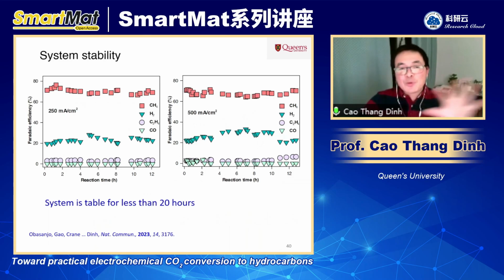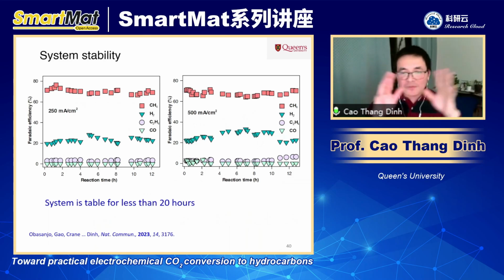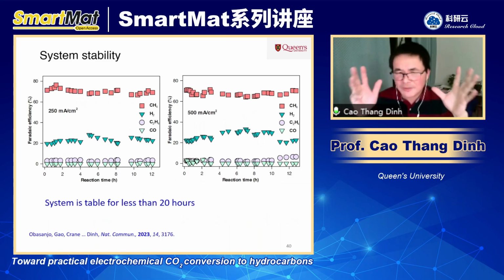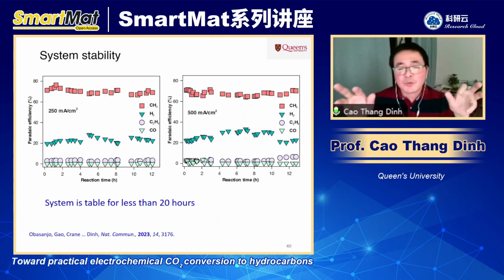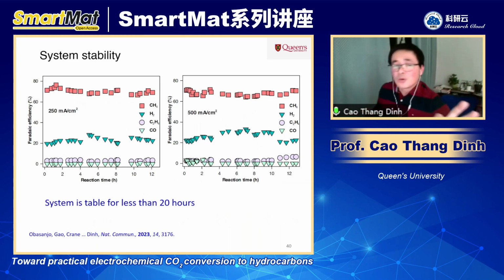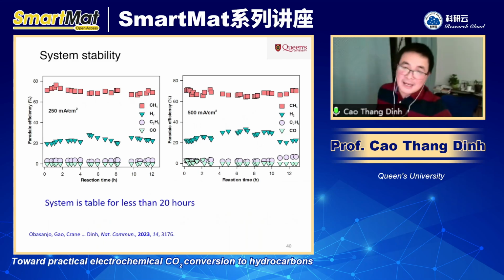So in the previous slide, I showed that for CO2 to ethylene, we can run for 100 hours. But in this system, we can only run for less than 20 hours. And in this work, we show here that we can run for 12 hours at 250 milliamp, and also 12 hours, a little bit more than that, at 500 milliamp current density. The methane is stable at 70% in both cases.